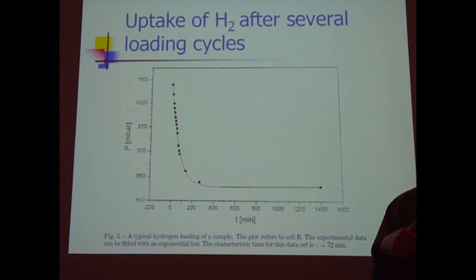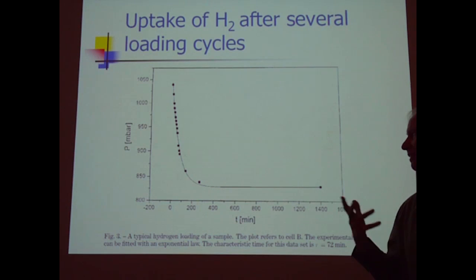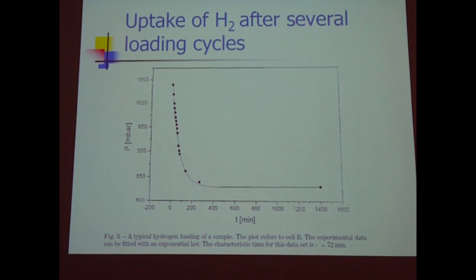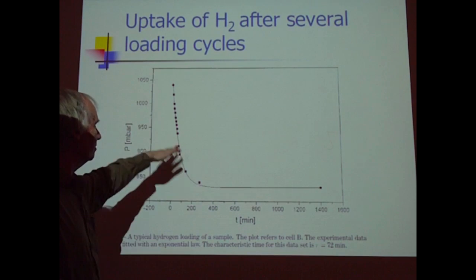You go back and you read and talk to people and so forth, and they have a loading protocol to prepare their nickel. So what they do is they introduce the hydrogen, they heat it up, then they let the hydrogen go out, and they try loading it again, go through cycles. So pressure, depressure, elevate the temperature, burn off the oxide layer, and go in and out. And it might do from 6 to 10 times cycling. And what they see is that on each cycle, the loading increases a little bit. So by the time that they're done with their cycles, they're getting a substantial amount of loading.